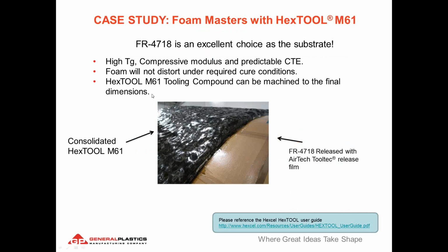Now, I want to get into a case study where we actually used HexTool M61 from Hexcel as a foam master. So 4718 is an excellent choice for the substrate for a lot of the previous slides' description. It has a high Tg, compressive modulus, and a predictable CTE. And the foam will not distort under the cure conditions. The HexTool M61 tooling compound can be machined after post-cure to the final dimensions. So therefore, any anomalies in the foam growth over a complex shape can then be corrected for by your machining operation at the end.